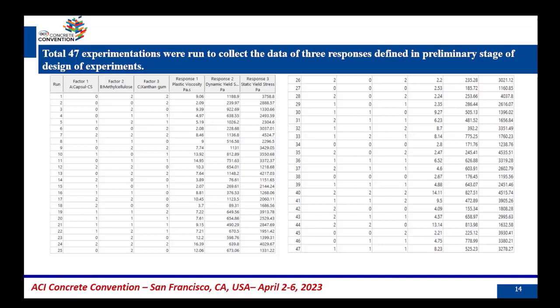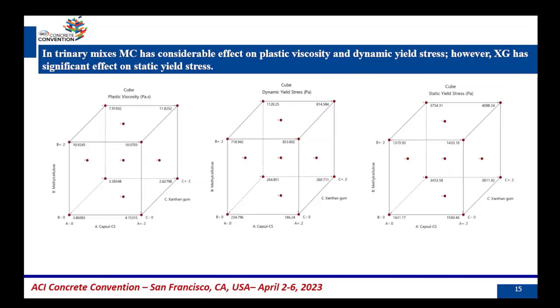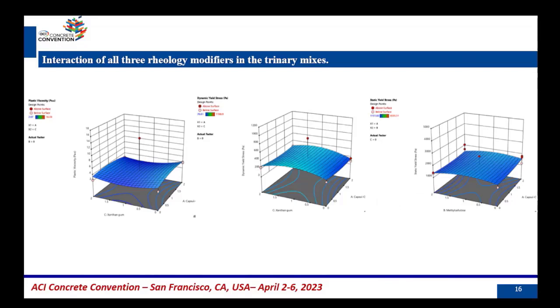So as an initial input, we use Design Expert software, and a total of 47 experiments were done to collect the preliminary data for three responses: plastic viscosity, dynamic yield stress, and static yield stress. If we talk about the interaction of the three different materials in the system, there were different behaviors that we can see. Methyl cellulose has a considerable effect on plastic viscosity and dynamic yield stress when we keep the cornstarch and xanthan content constant. But if we talk about the static yield stress, xanthan gum has a significant effect on the rise of the static yield stress in the system, and we can see this here in this